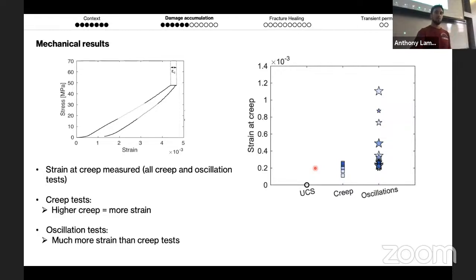Then when we have the oscillation, what's striking is that we have a lot more, at least twice as much, or 2 to 3 times as much strain at creep than during the creep test. There does not seem to be a clear correlation with the size of the oscillating event, or the creep dependence here. So basically no color or no size arrangement in here. The only thing that's striking is that it's a lot bigger strain at creep during these oscillation tests.